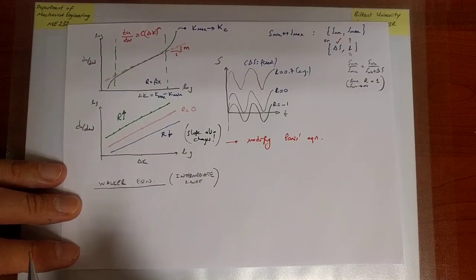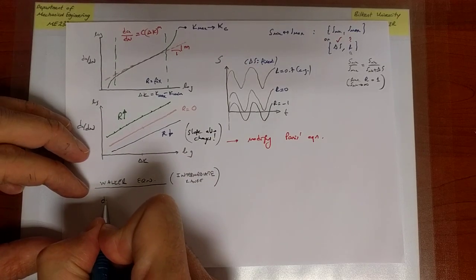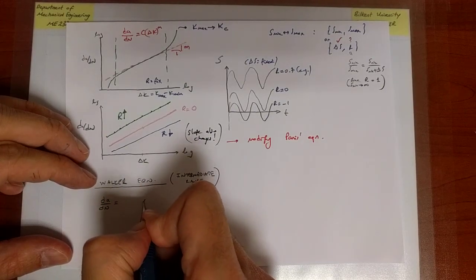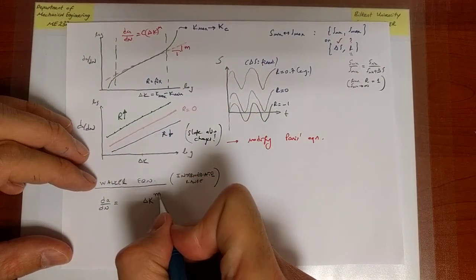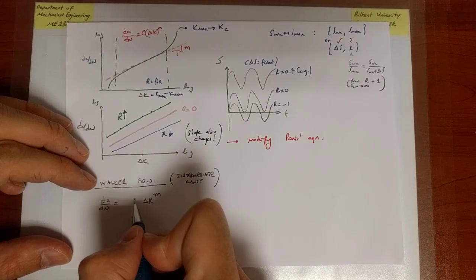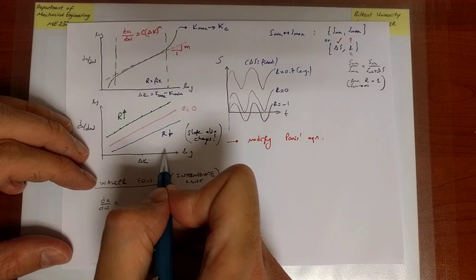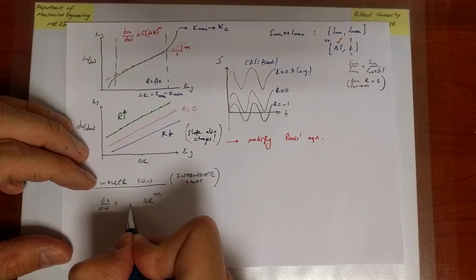And the Walker equation says the following. Well, the Paris equation said that the crack growth rate is proportional to delta K to some power. Depending on the value of R, this slope is not going to change. In reality it does, but we're going to omit it. But the factor increases if R increases and it decreases if R decreases. So here I'm not just going to write a constant.